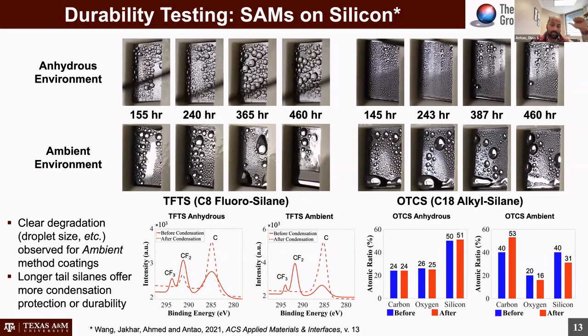you'll see that the longer tail silanes actually performed better. In this case, the alkyl silane, even though the fluorosilane has better wettability properties that you would want. It has a slightly higher advancing angle and a slightly smaller contact angle hysteresis compared to the alkyl silane. The alkyl silane actually had better performance in terms of degradation or durability after condensation.